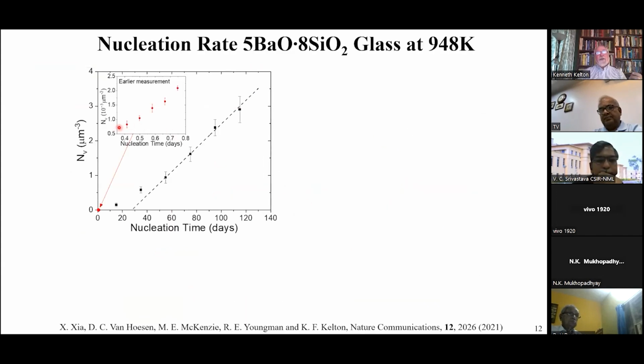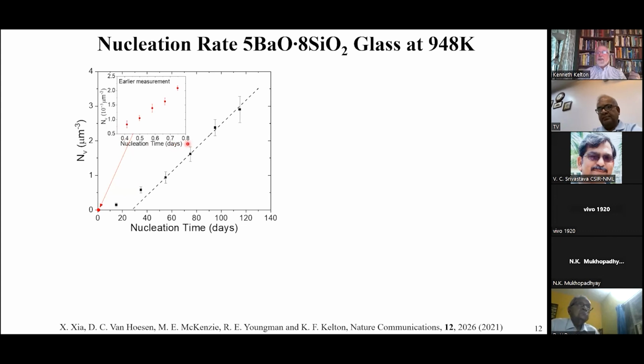Well, it kind of looks like what I showed you, the number versus time, and this is nucleation time in days. It starts off low and then gets to a steady state value. You extrapolate that back to the axis, you get the induction time, and the slope of that straight line is the steady state rate. But the problem is these data fit into that data point if we extend the amount of time that we measure at the nucleation temperature. So now instead of 0.8 days, these data go to 140 days.